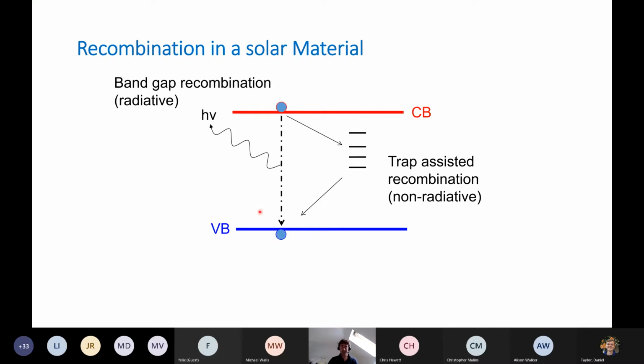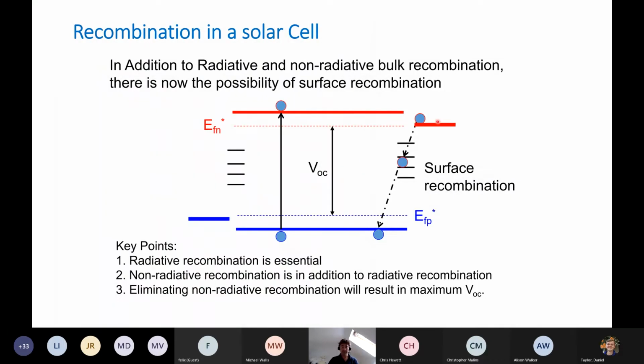In addition to recombination and losses within the absorber layer, when we put interface materials on, when we put electrodes on, when we put charge extraction layers on, we can have further surface recombination or losses at the interface. So what we have to do when we develop these materials is try to minimize the defects in the bulk of the semiconductor and try to minimize these interface or surface recombinations.